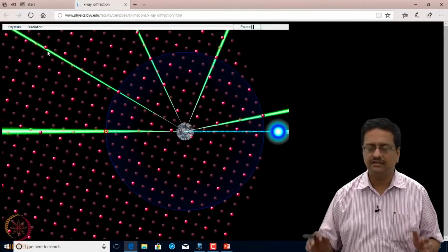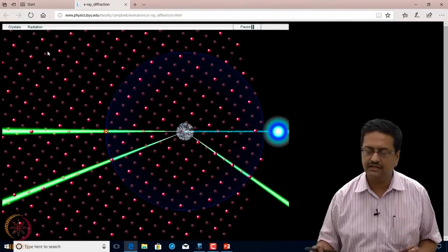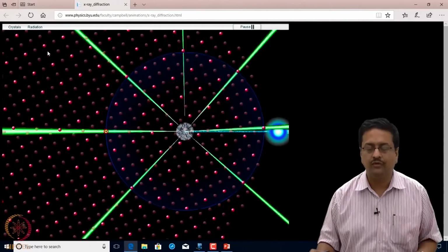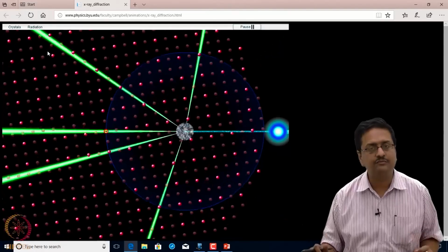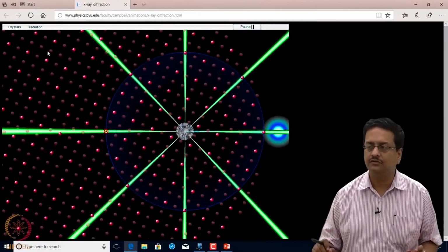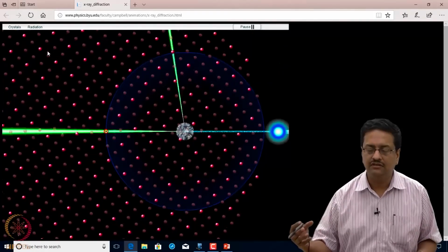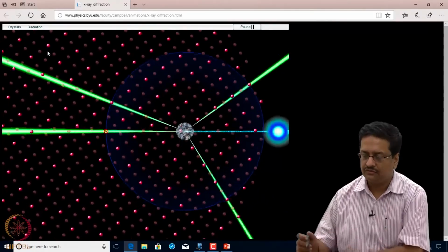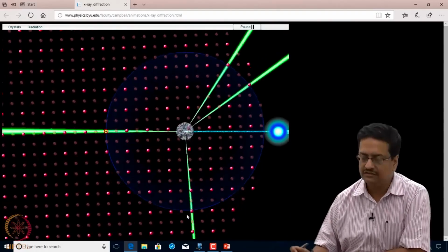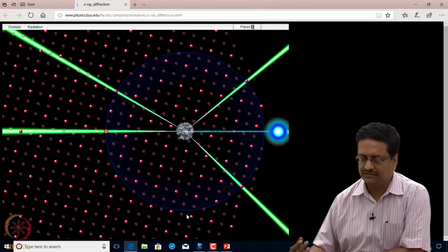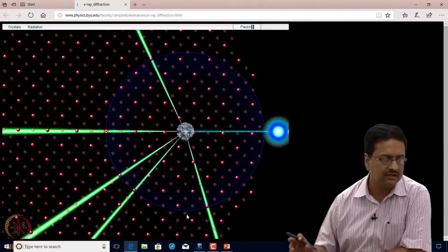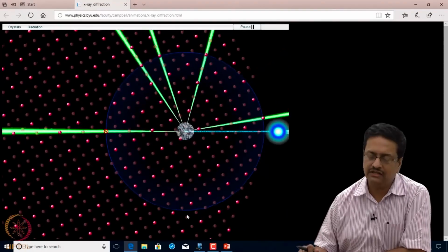here what you can see is a zinc blende crystal in a particular plane, and in the reciprocal lattice you can see some bright red spots and some red spots which are not bright, which have sort of disappeared. When those bright spots are crossing the Ewald sphere, it is making a diffraction, and when those dull spots are crossing the Ewald sphere, it is not making any diffraction.